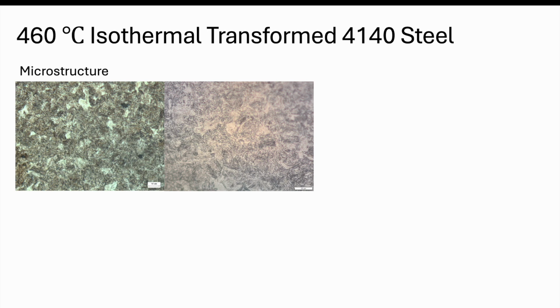So this is our microstructure. You might be able to see a little difference. It's kind of difficult to see. Sometimes you can actually see some ferrite, some of the lighter regions. This might be a little ferrite that's present in the structure, but it's still a very fine structure that's very difficult to tell. It can often look a little bit like martensite, even a little bit like pearlite, but you see it's kind of a dark and light region here with different phases. That is the ferrite and cementite. That's the bainite structure. It's very small.